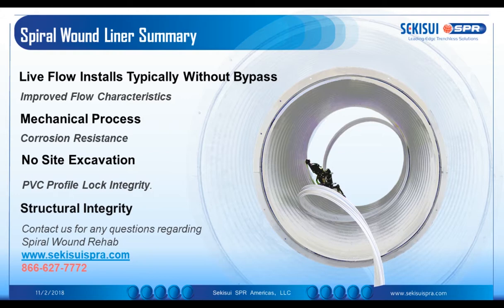If I can add to that, because it is one very important factor, after lining it is important what cleaning equipment you do use. After lining, as with most liners, we don't recommend the use of mechanical cleaning devices, chain flails and rotor rooters and so on. We really do recommend water jetting, and we limit the pressure from those water jets typically to 2,000 psi. It really is important not to use mechanical devices within rehabilitated pipes.